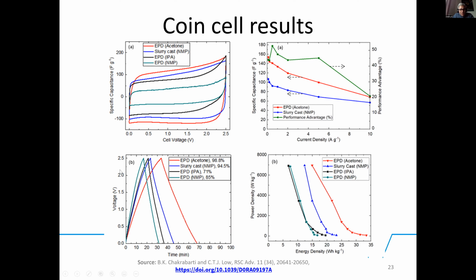And when we did charge and discharge at 0.1 amps per gram, again the EPD electrodes using acetone as solvent were giving better performance in comparison to the slurry cast standard electrodes. Slurry cast electrodes perform better than the other solvents, but the acetone was giving much better than the slurry cast. Then we did rate capability studies